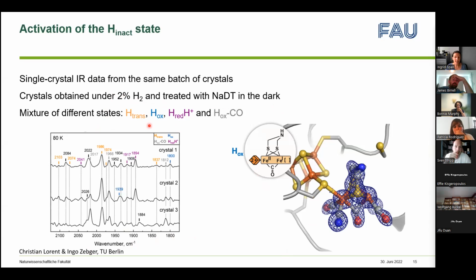So H-trans still has a ligand. So this is not quite in agreement with our ligand disappearing. So potentially, we also have some help from synchrotron radiation to get rid of the ligand. We don't know. We also see a small portion of CO inhibited enzyme. This also means that we expect a diatomic ligand, and we see evidence for HOX and HRED plus in the IR spectra of the crystals.